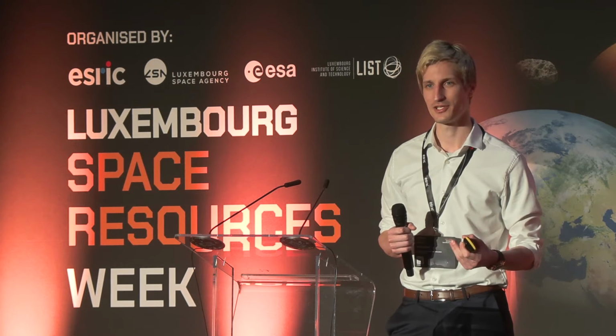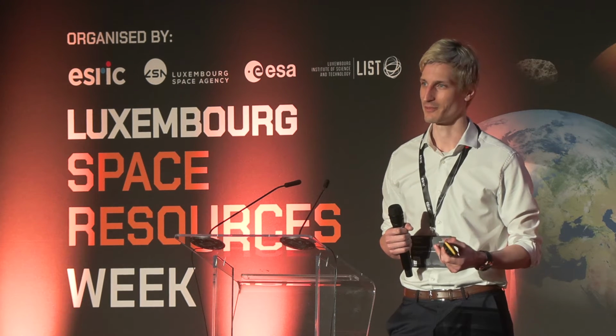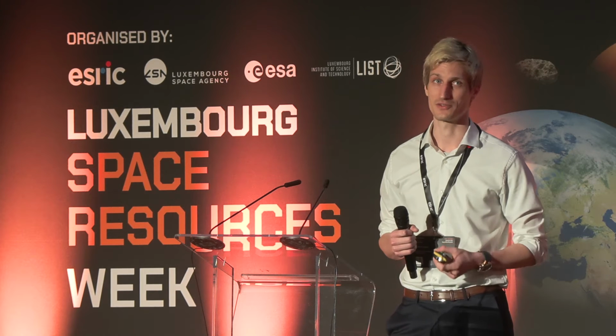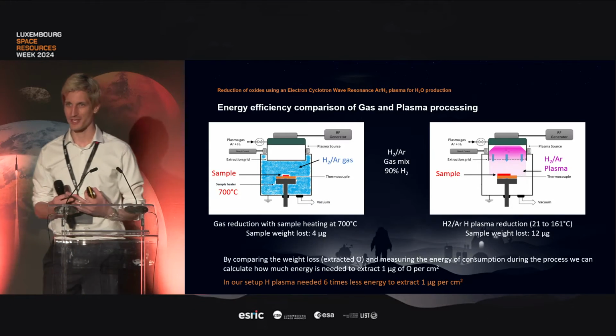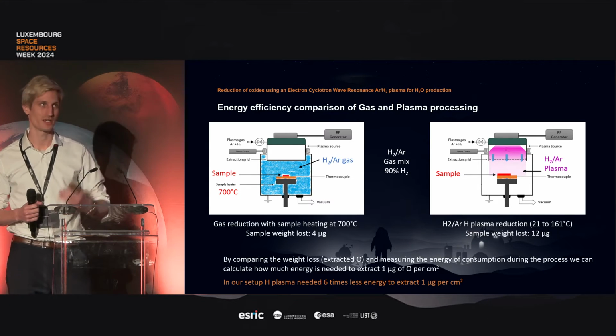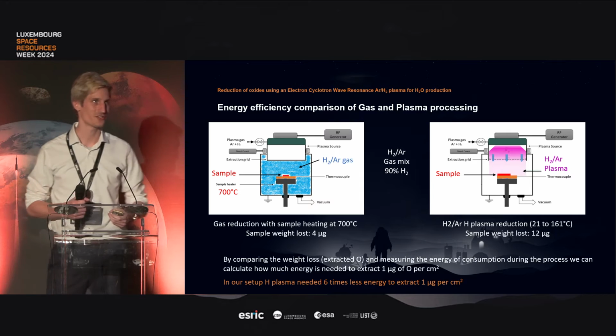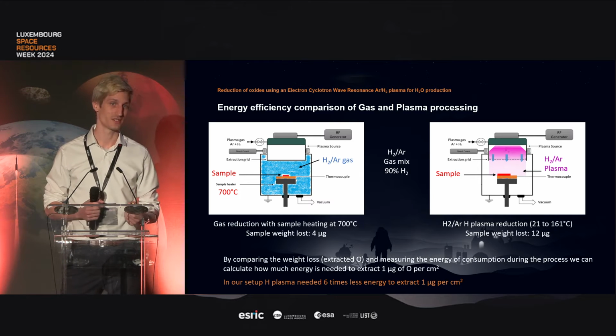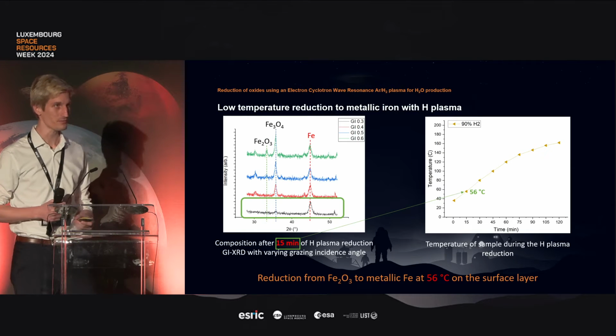This gave us a metric to compare it. We obtained how much energy we use to extract 1 microgram of oxygen per centimeter square. When we put the numbers together, we get that plasma, in our case, in this preliminary investigation, is using 6 times less energy than a gas reduction process to extract 1 microgram of oxygen per centimeter square.